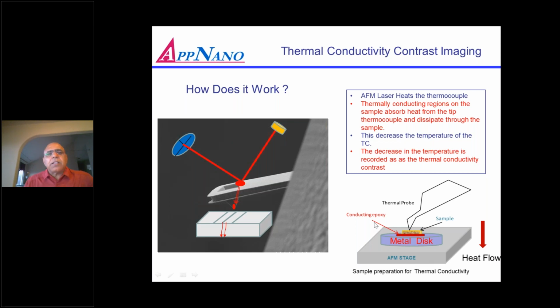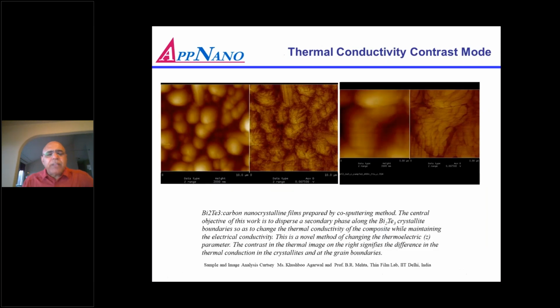So this is the thermal conductivity contrast. We did some images, like this is one of the bismuth tellurides used for thermoelectric materials. And this is bismuth telluride and carbon nanocrystals. They're co-sputtered together and then heated. Once they are heated, you can see in topography, you don't see those grains which you can see here in the thermal image. And this is a zoom in of those. So if you zoom in further, you can see there are the grains.